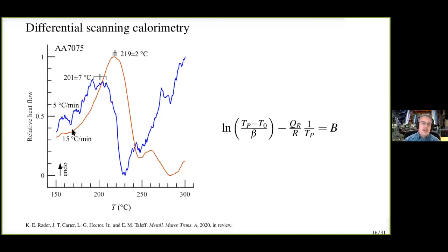Now, you get characteristic curves like this red curve here. As I increase the temperature at this particular heating rate, the heat flow, this is a relative heat flow measure, increases as I approach this temperature right here. And I get a peak heat input required at this temperature that then drops down. Well, what's happening here is that at this temperature, we are dissolving some of our precipitates. So this is an energy going into dissolving the precipitates.